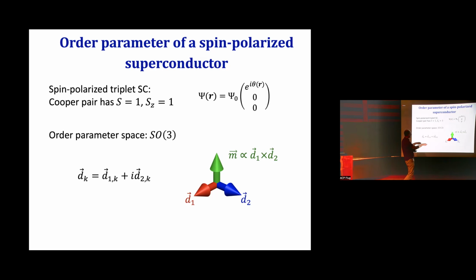An SO(3) matrix, I can specify by a triad of vectors, which are mutually orthogonal, and so at every point in space, my superconductor is characterized by this triad. The ground state would be uniform, but if I have thermal fluctuations, for instance, it would fluctuate from point to point. And as we know, this in particular means that in 2 spatial dimensions, because you cannot break a continuous symmetry, there actually should be no finite temperature transition at all. But let's imagine, so Tc is 0, the superconductor can only exist in the ground state, but I'm going to ignore this fact now. I'm just going to assume that at low enough temperature, my system is big but finite. The correlation length of the superconductor is much bigger than the system. It behaves as if it's a superconductor.